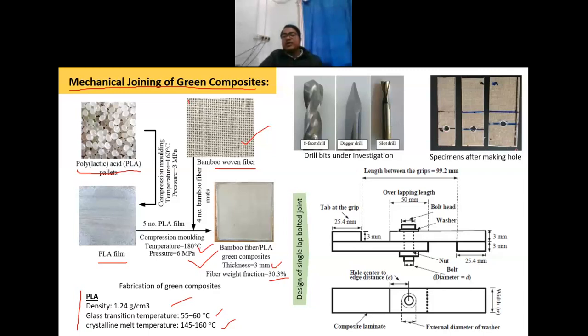specimens having different width. As I have mentioned, this is a mechanical joining technique, so first you need to create the hole. Creating a good quality hole again is a challenge, and we have considered different parameters so that we can create good quality holes in this composite material. I have already discussed how the different drill point geometry, feed and speed all affect the hole making performance of these composite materials, so I will not repeat this part again. We have created holes by using different drill point geometry and considering different levels of feed and speed, and then we found the optimum parameter.